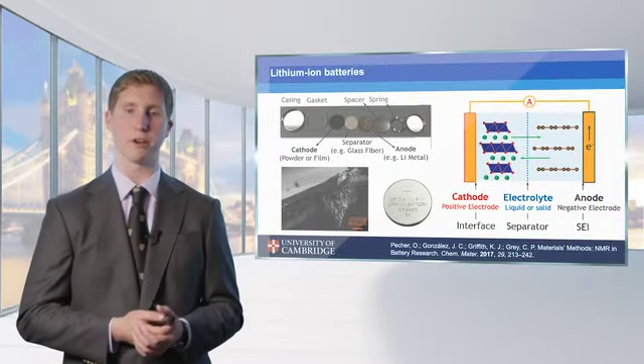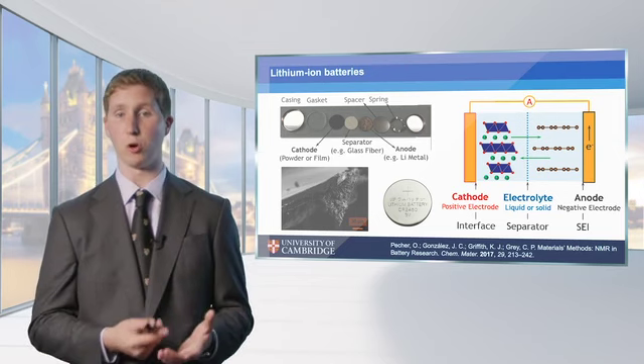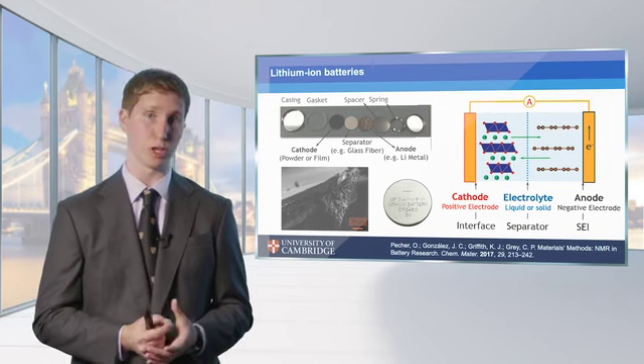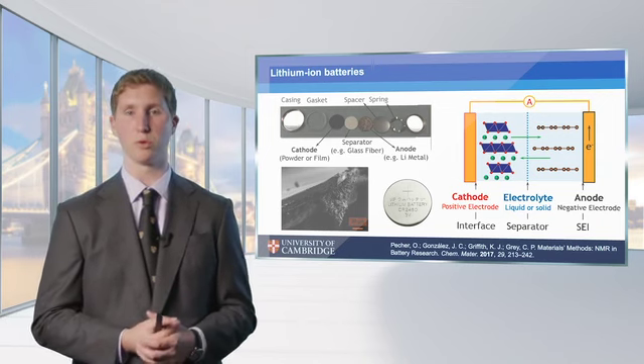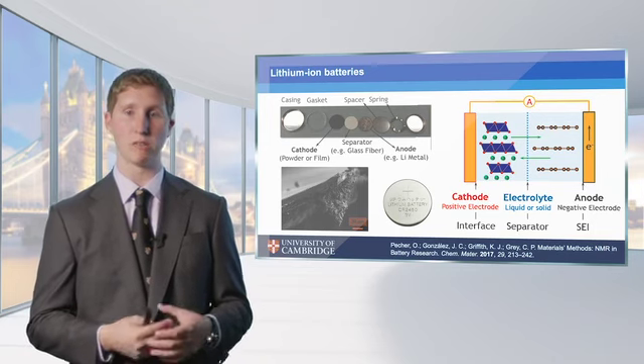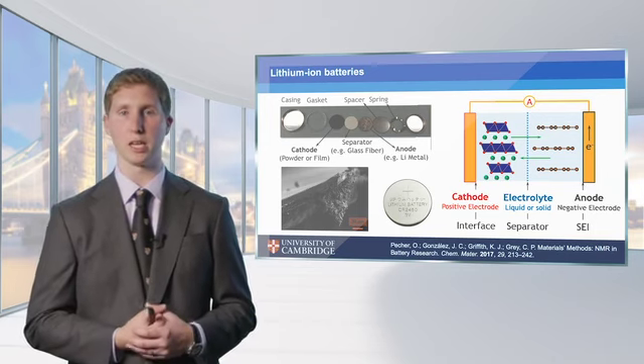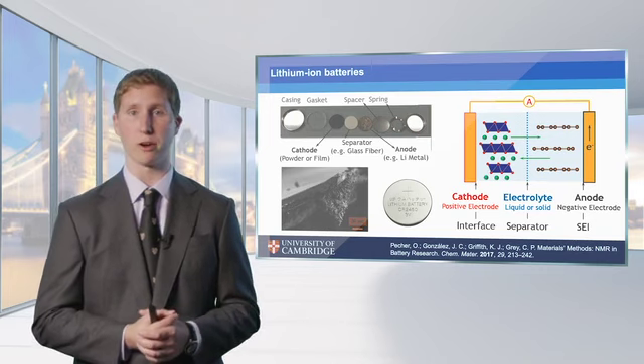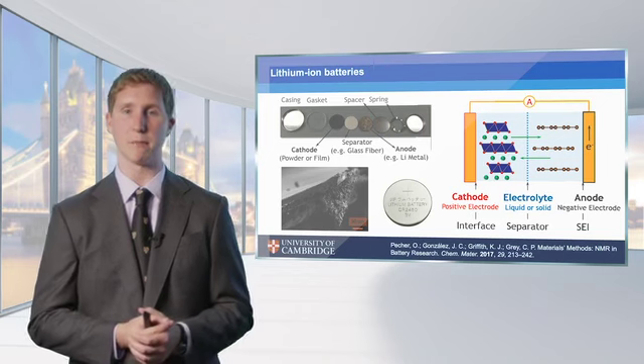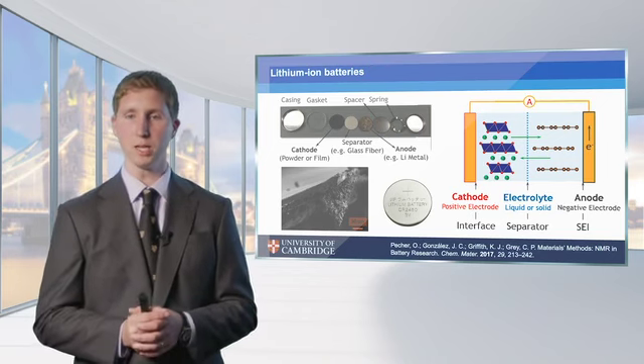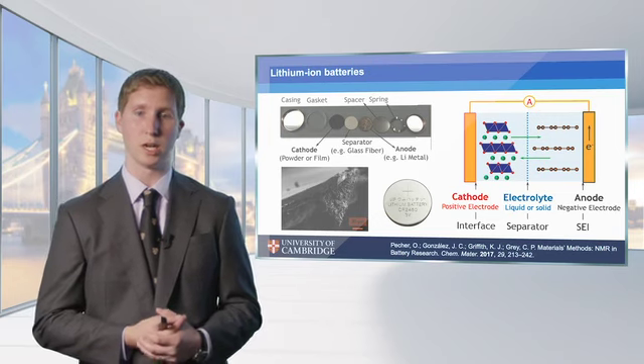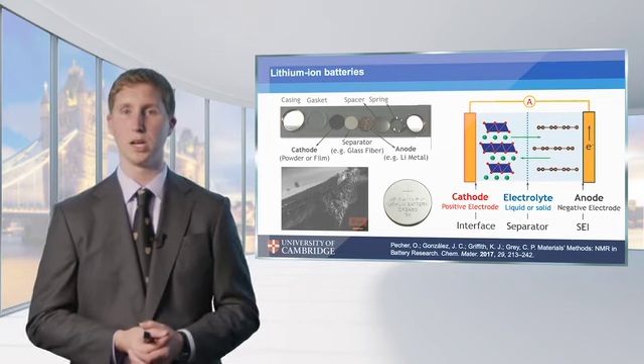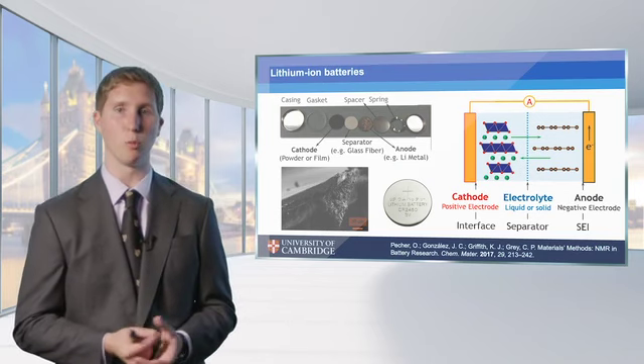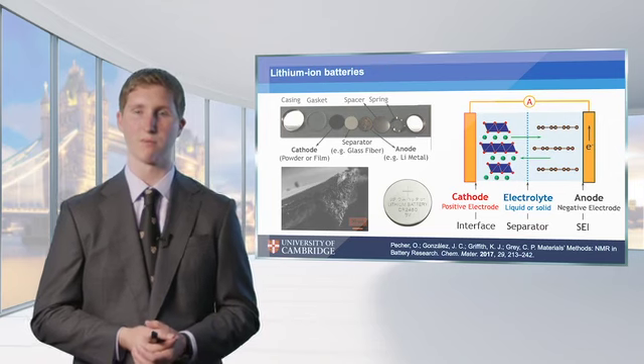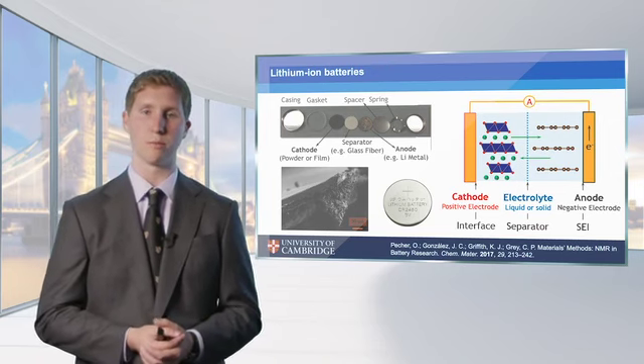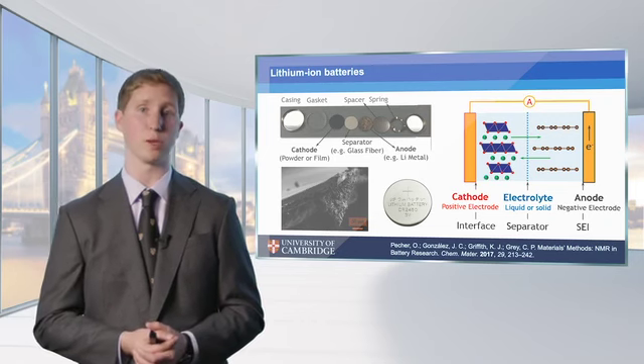In a conventional lithium-ion battery, the cathode we would have is lithium cobalt oxide, if it's in something like most of our portable electronics. For electric vehicles and other applications, we're moving more towards nickel-rich versions of a similar crystal structure, with nickel and manganese replacing most of the cobalt, in some cases aluminum. So these are NMC, NCA type batteries. But there are other cathodes as well. There's lithium iron phosphate for higher rate and for longer lifetimes, albeit at a lower energy density, and other cobalt-free cathodes like lithium manganese oxide, and some of the new rock salts based on manganese and niobium, for example.